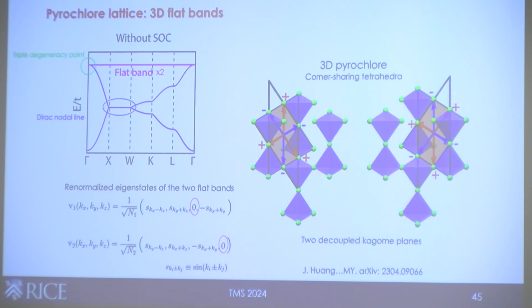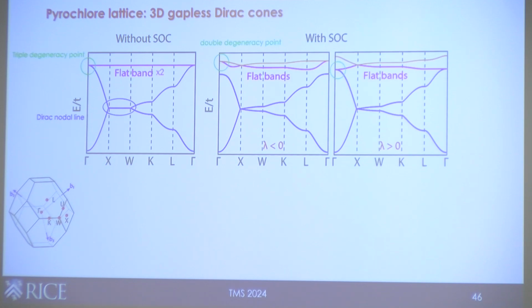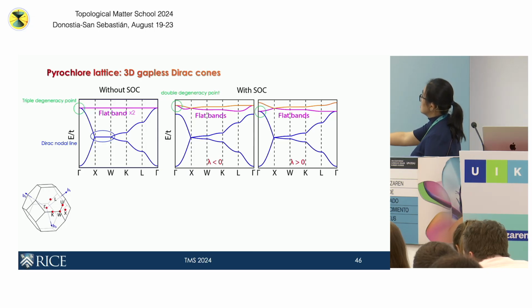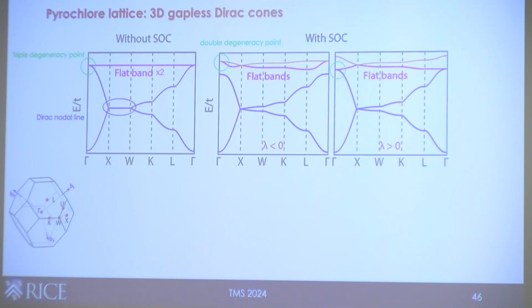In addition, there's some interesting things here: you would end up with a triply degenerate point at the gamma point, 2 flat bands and the dispersive band, and then you will have a Dirac nodal line along some path of the momentum of the Brillouin zone. Okay, so this is what happens without considering spin-orbit coupling. If you put in spin-orbit coupling, there are different ways of gapping this. So you can have situations where the gap appears between the 2 flat bands and the dispersive band, or between the 2 flat bands. But in both cases, you will end up with a doubly degenerate point, the gamma point, associated with the flat band.